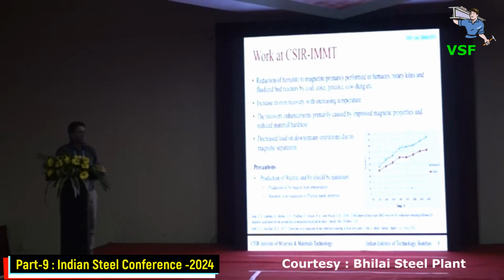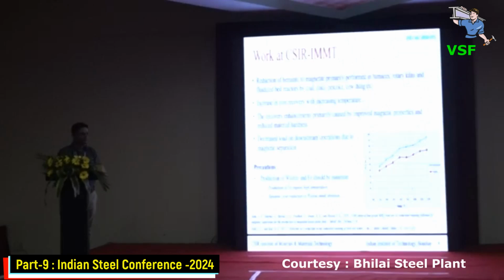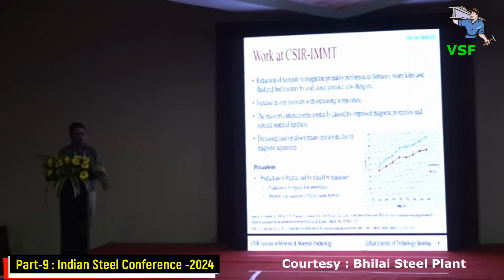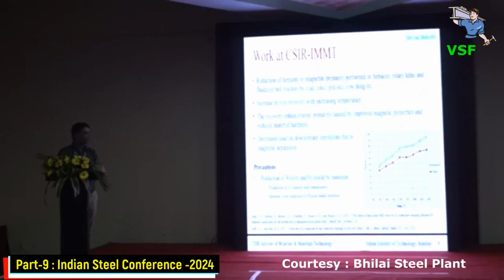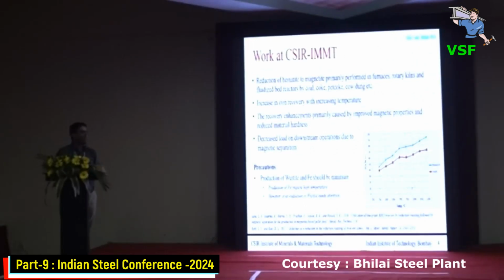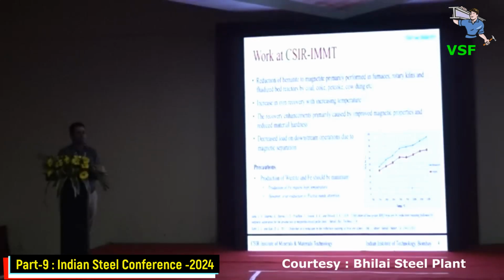So, CSIR has been working on this technology for a long time, and we have tried different reductants like coal, coke, pet coke, even cow dung and biochar for this kind of process, and it has been reported well in the literature. We have found that with the increase of temperature and reductant concentration, we are getting good results in terms of Fe grade, high grade, and recovery.